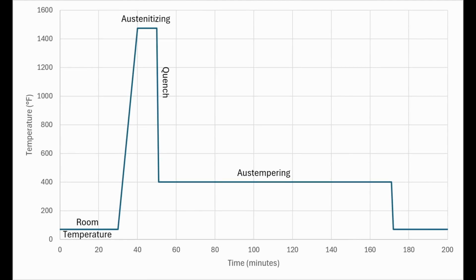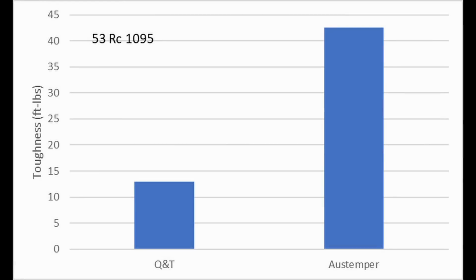The salts are fast enough for quenching most materials as long as the steel isn't too thick. The cross-section is small enough. So we can quench down to that intermediate temperature and hold for Bainite. Now, why would we want Bainite? Well, the big advertised property of Bainite from Austempering is improved toughness.